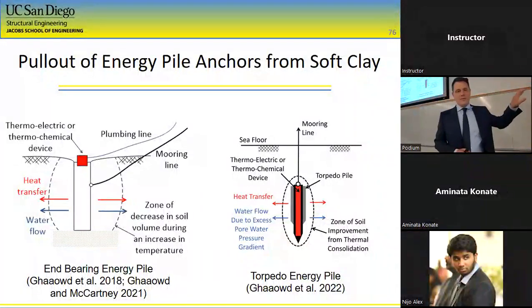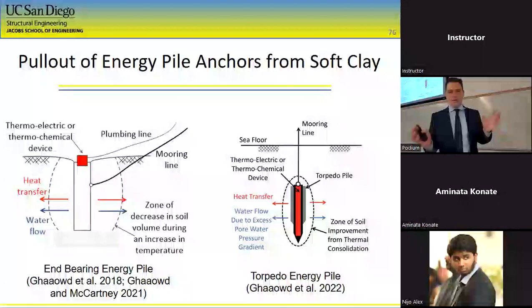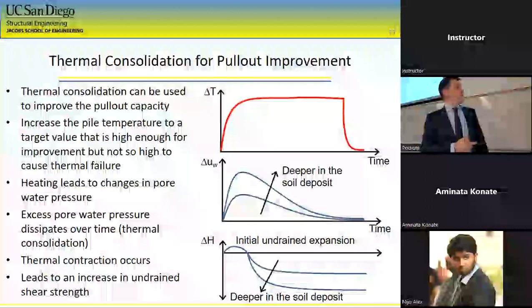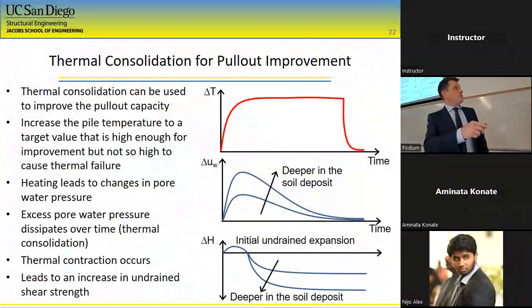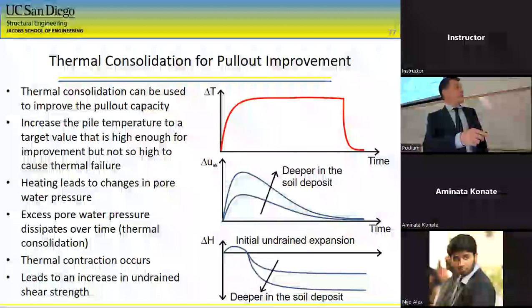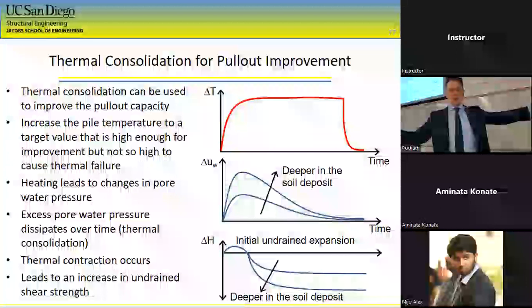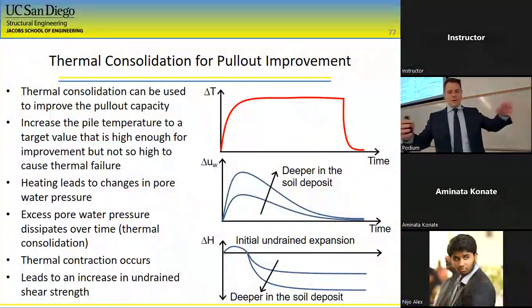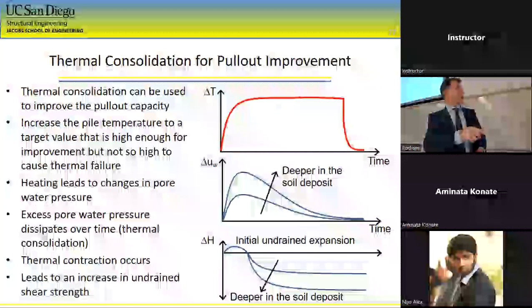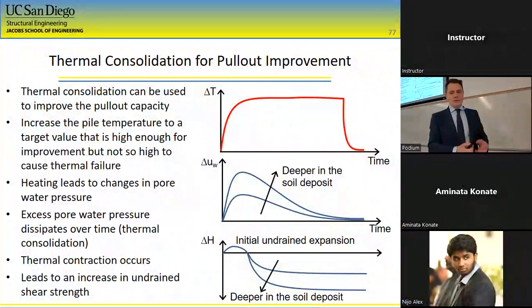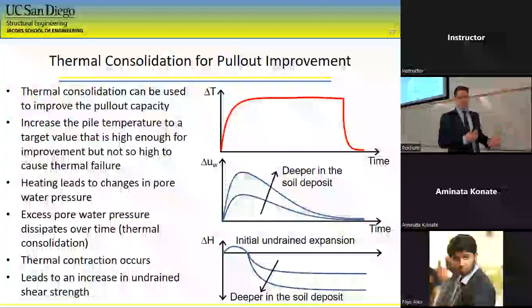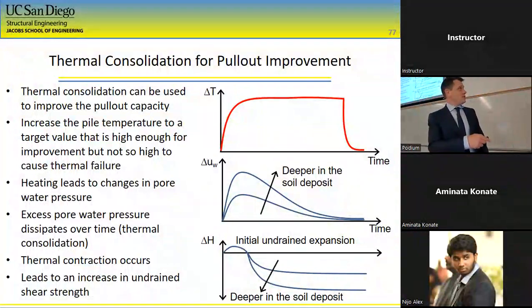So you're not necessarily trying to harvest energy in this case, but you're trying to use the heat to improve the ground. So the heat transfer goes away from the pile, and that's going to drive water away from the pile and cause consolidation. So that's kind of what's shown here. You increase the temperature of the pile, maintain it. The water pressure increases, and then when you increase the water pressure, that creates a gradient. So as the gradient dissipates, it goes down to zero, you end up having a consolidation process. So we call this thermal consolidation, and that leads to an increase in undrained shear strength.